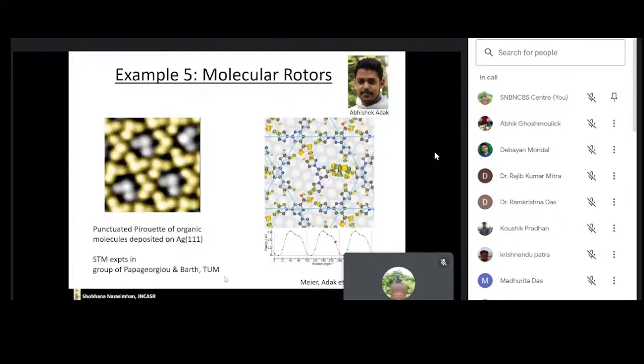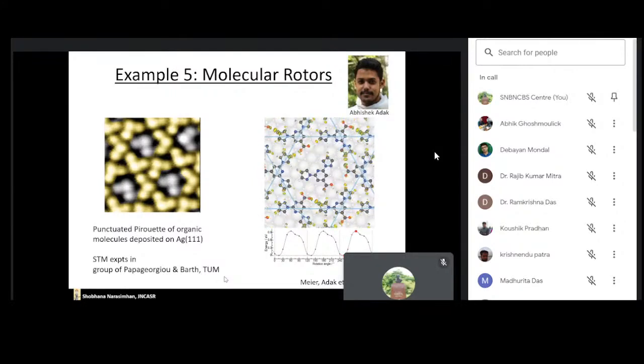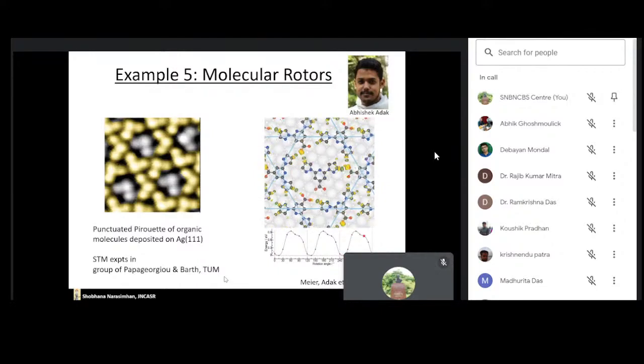And I haven't shown those results here, but you can deduce the barrier for the rotation from the experiments, and you can also compute the barrier from our DFT calculations, and they match almost exactly. It's about 0.94 electron volts. This structure also has some interesting chiral features, which I won't go into.